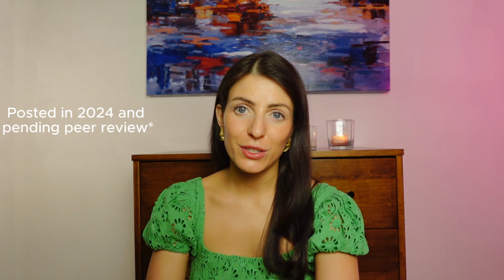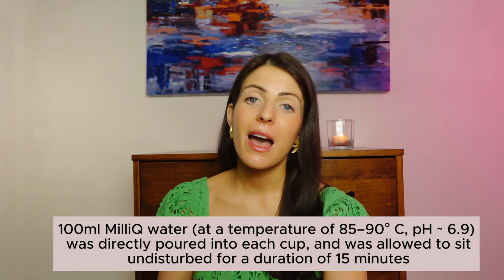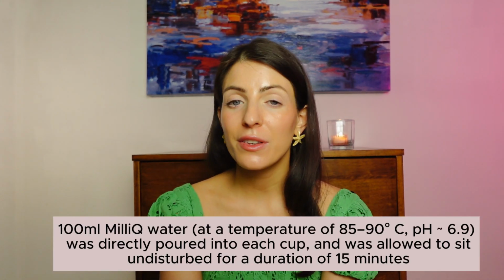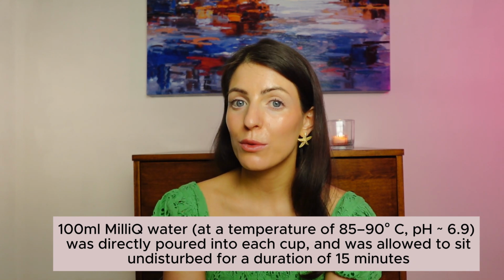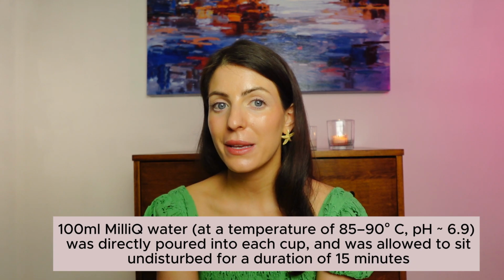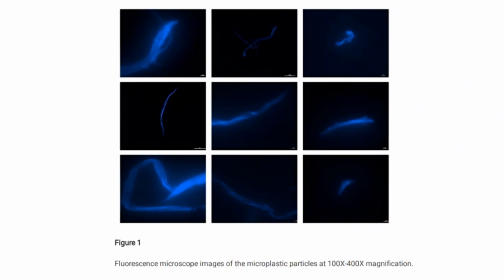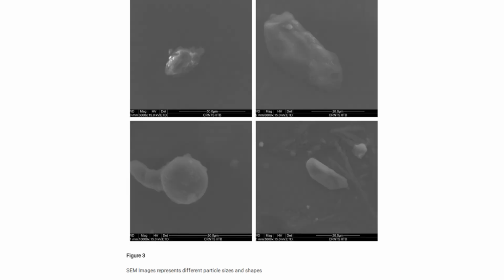So this first study is titled Quantification and Size of Microplastics Leached from Disposable Beverage Cups. It was observed that about 6,000 particles of microplastics could be observed in 1 milliliter of sample after exposure to disposable paper cups. After 15 minutes of exposure time, microplastics could be observed with fluorescence microscopy and scanning electron microscopy. The microplastics had defined shapes like spheres and rods, and also irregularly shaped particles. The size distribution of microplastics was primarily 2 to 5 micrometers range, with a small fraction of particles larger than 15 micrometers. Based on spectroscopy results, the composition of the released particles was found to be indeed HDPE, high-density polyethylene, which is the lining of some of the paper cups.